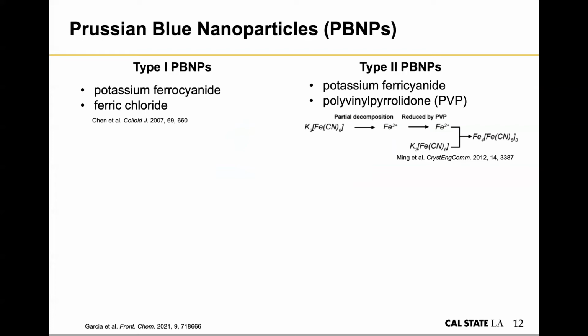It can gradually decompose the potassium ferricyanide existing in the solution, and then the iron 3 will combine with the iron 2 in the presence of PVP, so they call it a surface control method. With this method, you're expecting to synthesize cubic-shaped Prussian blue nanoparticles. Whereas the first one generates more random shapes.